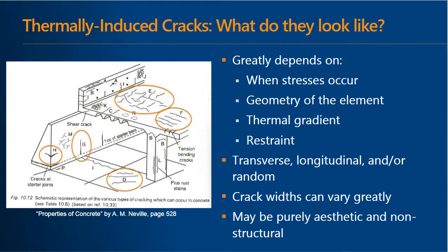So the other cause of early age cracking that I showed in those field photos could be thermally induced cracks. And we feel that thermal cracks really don't get enough credit. And I'll discuss why on the next slide. But the presence of these cracks greatly depends on when the stresses occur as it relates to concrete placement and hardening, the geometry of the element, the magnitude of your thermal gradient, and restraint in the structure.